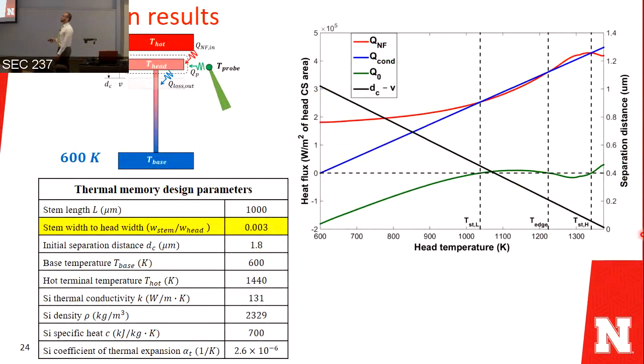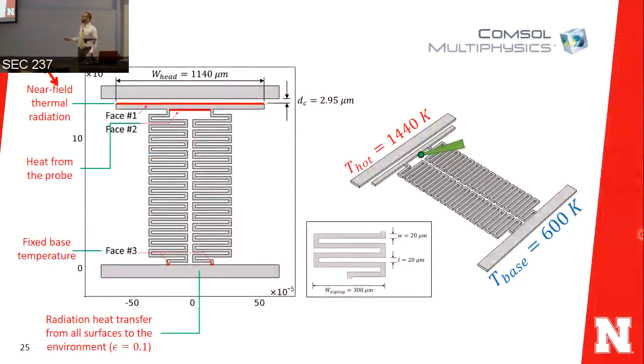We have solved this 1D model for that system and keep the base at 600 Kelvin, and they give profiles for heat such as shown here. This is very similar to the cartoon I have shown in the previous slide. However, there is one drawback of this system, that the width of the stem, which is the support to the head, is very small. Why is this? Because the conduction is way stronger than radiation, so you need to limit the heat conduction to make it interact with thermal radiation. To solve this problem, we have introduced a 3D model for a practical design.